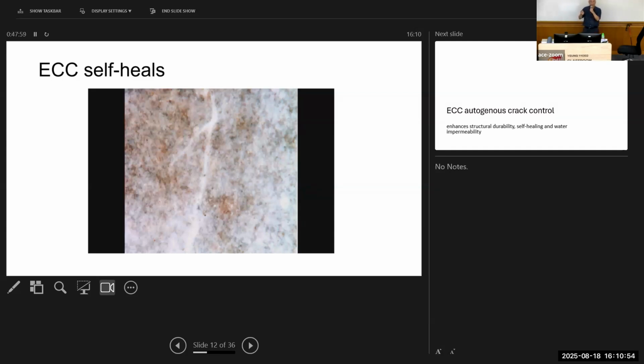The problem is, in general, for normal concrete, cracks can be very large, right? Even with steel reinforcement, it's not going to be less than 60 microns or even 20 microns that I showed you. It will be hundreds of microns. And then there is no way to regrow those materials that fills up the whole gap. And there are no such forest of fibers I was talking about. But I'm just making up a story for you.